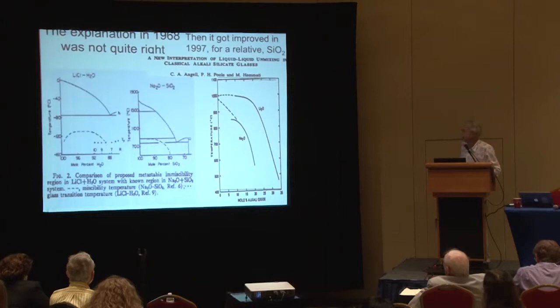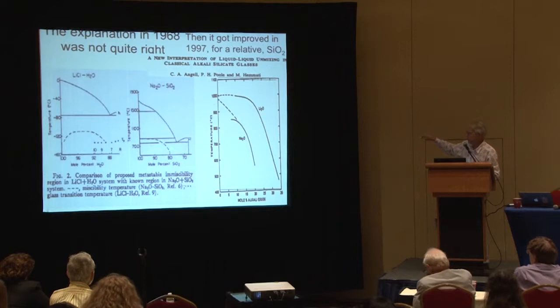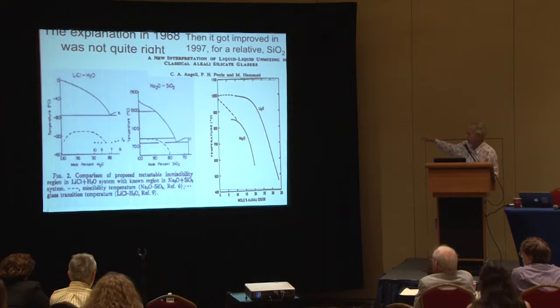And that's because you've had a lot of vitreous water separate out. This is our first attempt to explain this phenomenon, which wasn't quite right. The idea being that, like the case of silica, where it was known that you could get droplets of silica in your window glass if you look in the electron microscope, we said the same sort of thing here, but we thought it was a composition-driven thing with a maximum in the phase separation domain away from water. Now we realize it's not like that at all.